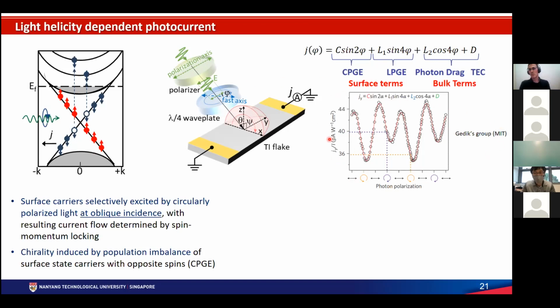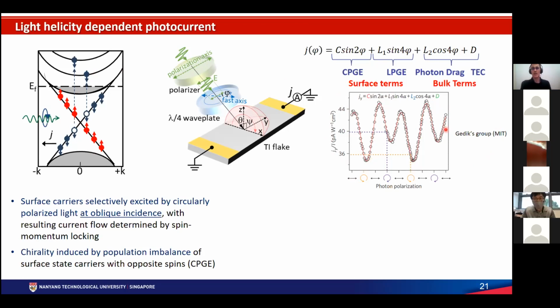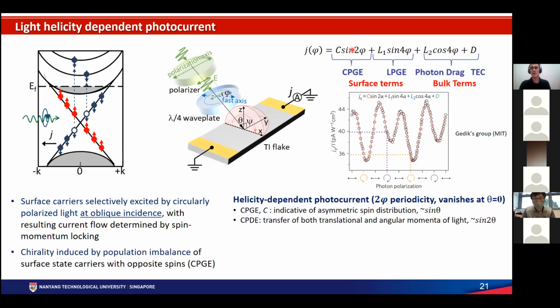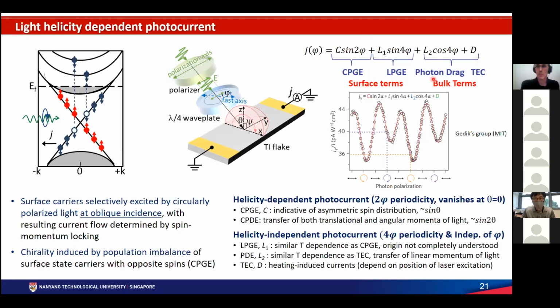So when you do this experiment, you will observe a curve that looks roughly like this. So the current is a bit richer than just the response to the circular polarization. You have mostly 4 components, 2 of which are surface terms and 2 of which are bulk terms. You have a periodicity that goes as 2 phi when you rotate the polarization axis, and you change from linear to right circular to linear to left circular polarized light. And then you have another periodicity dependence, which is a 4 phi, and one that is independent of phi, which is a bulk contribution, a thermoelectric contribution. What we want to focus on is specifically the 2 phi periodicity here.